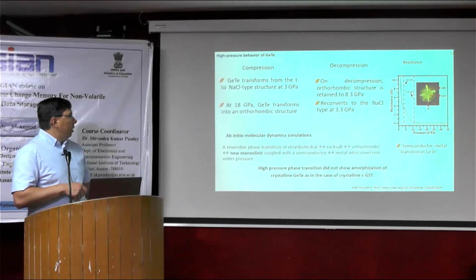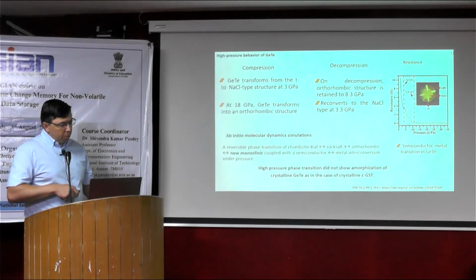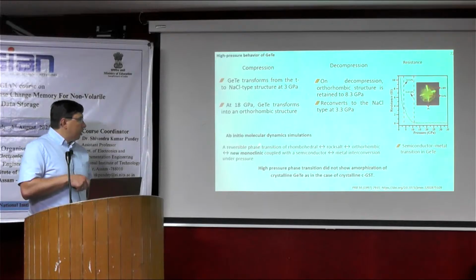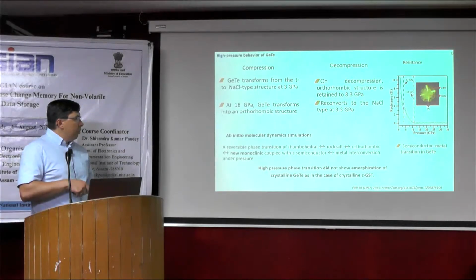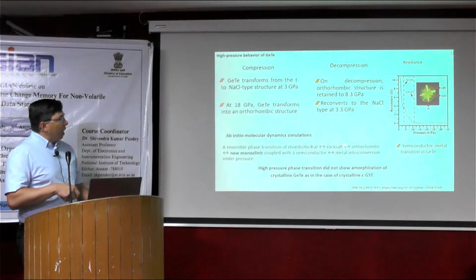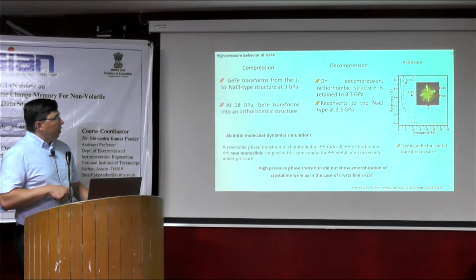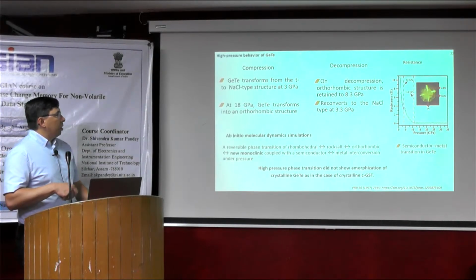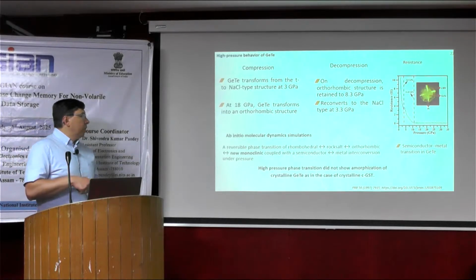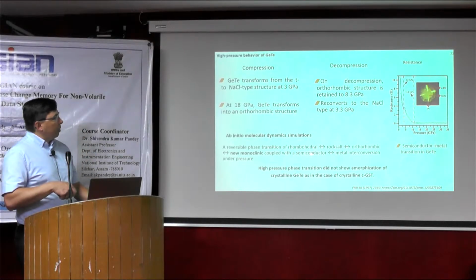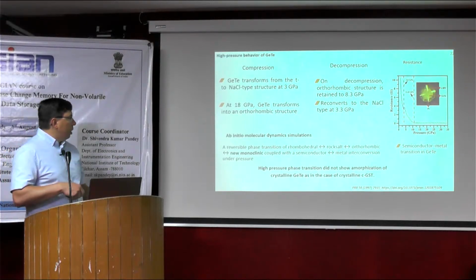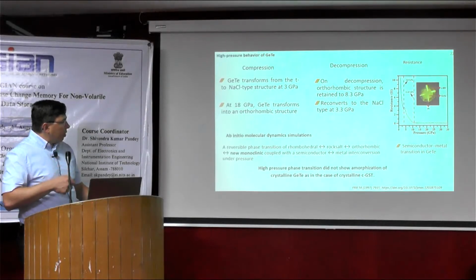Ab initio molecular dynamics simulations, however, suggest some reversible phase transition from rhombohedral to rocksalt type structure, confirming this result. Then to an orthorhombic structure, which is also observed experimentally, but then they observed a new monoclinic structure having semiconductor and metal interconversion under pressure. So they observed the formation of a new phase, which was not observed experimentally.